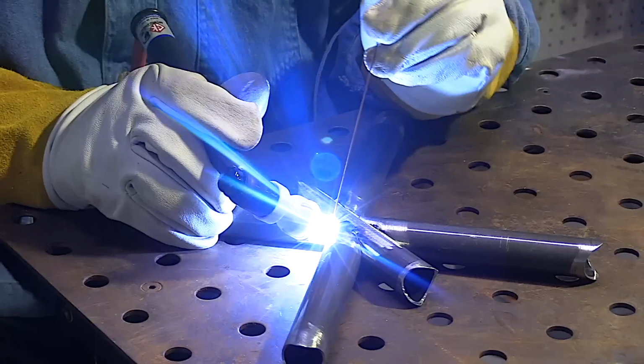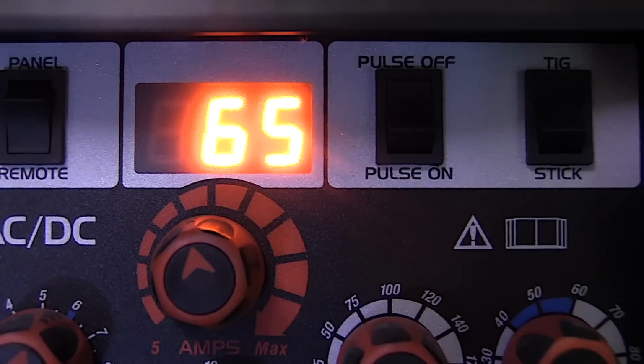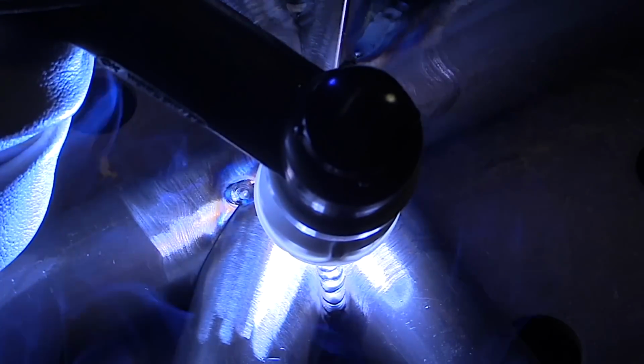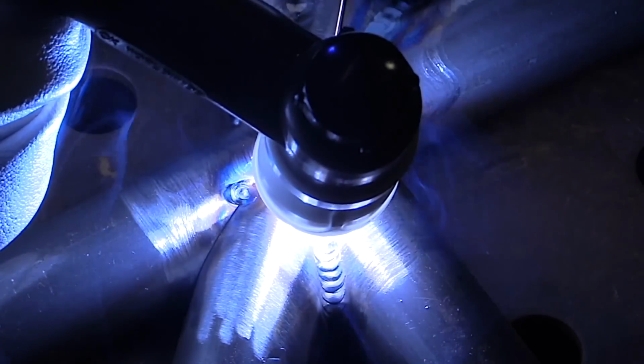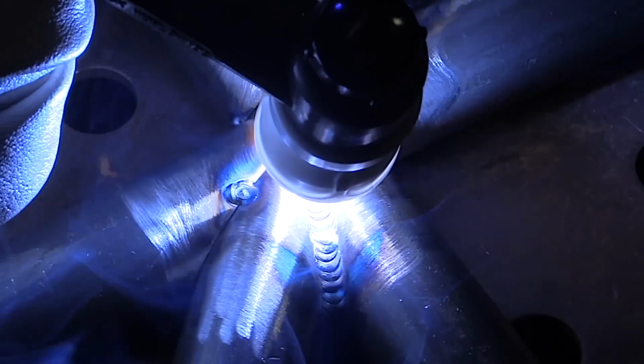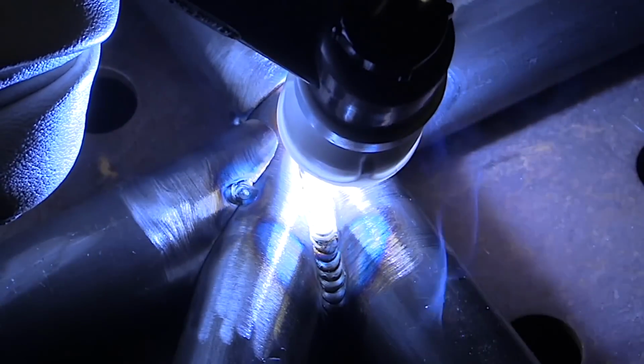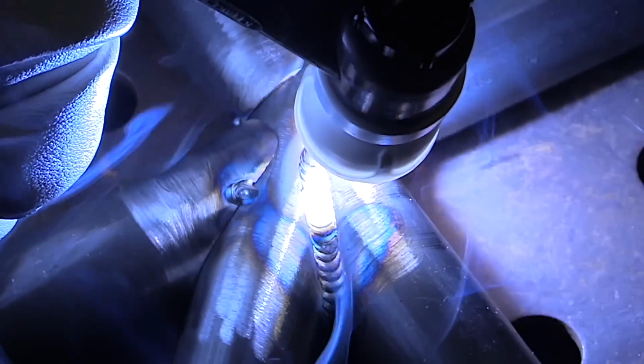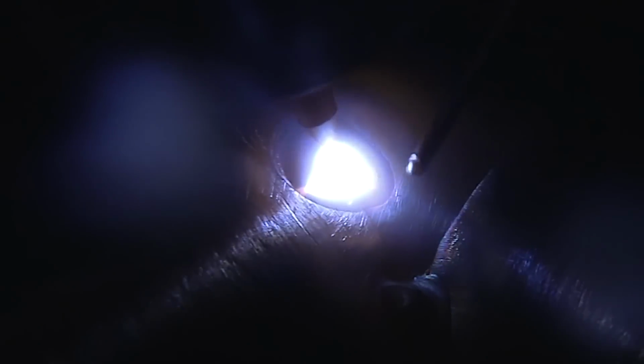It's around 0.063 wall thickness. That's 1.6 millimeter wall thickness. There's a rule of thumb that use 1 amp per 1,000ths of thickness, so I'm at 65 amps here. That's pretty close. It really helps to clean the mill scale on 4130 chromoly tubing. Also helps to have a good cup, a good argon shield.